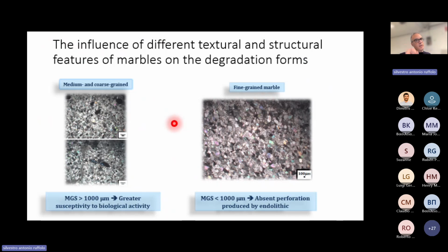A very interesting thing that we have observed: we have observed many biological degradation patterns on marble, and we observed that a fine-grained marble is less prone to be attacked by endolithics compared to medium and coarse-grained. So the bigger the grain size, the higher the endolithic attack. It's a very interesting thing.